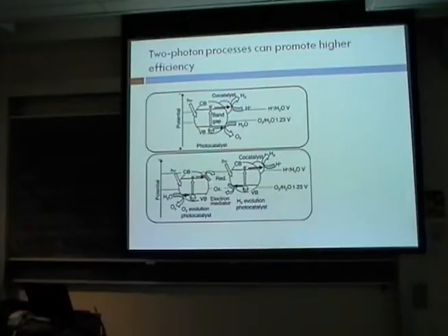And so this compound, whatever it is, will pick up the electron through a reaction and then carry it over here and react with this co-catalyst to release the electron, or to combine with this hole that's being produced here, in order to be oxidized and then continue this cycle. This hole that it reacts with has been produced through a second photon that's hit this other co-catalyst to generate an electron that's of higher energy than would have been available from this material, that can react with your protons to make hydrogen.